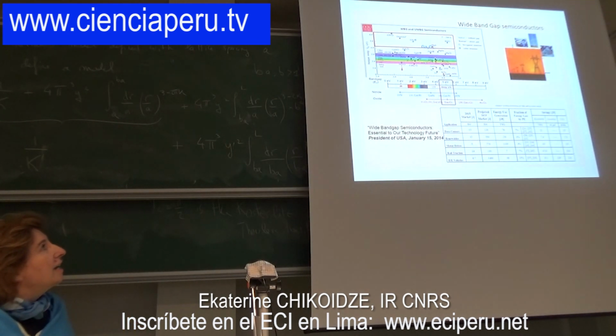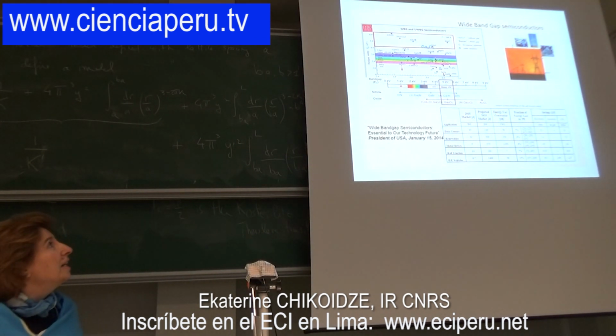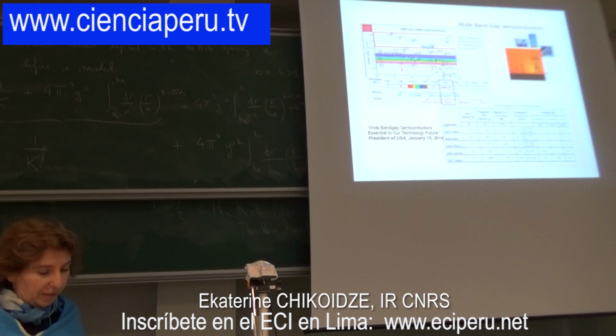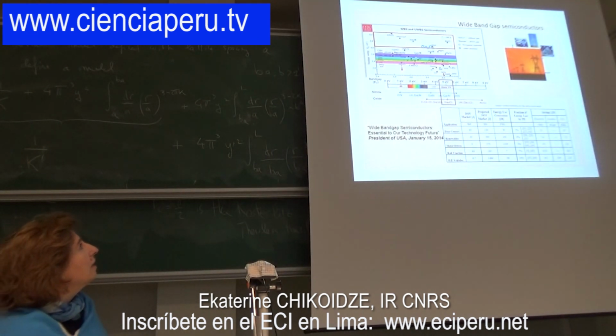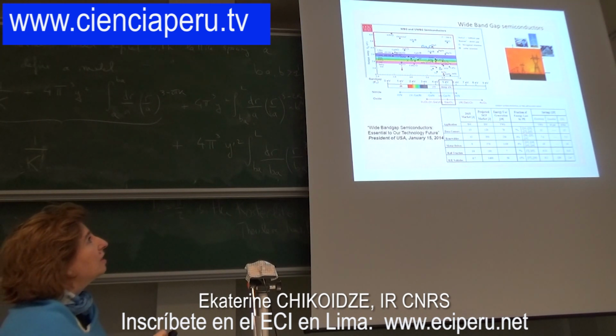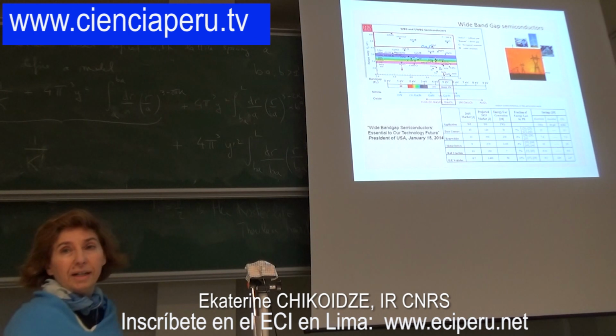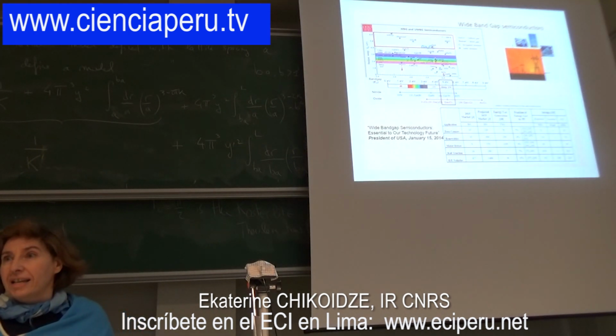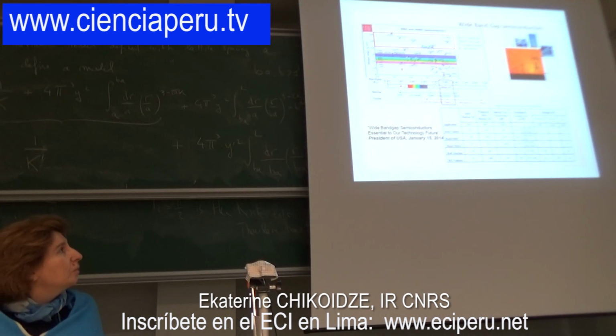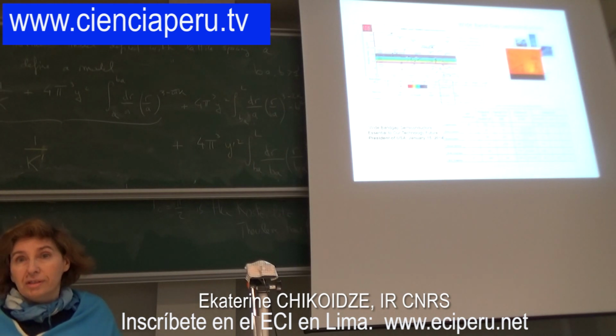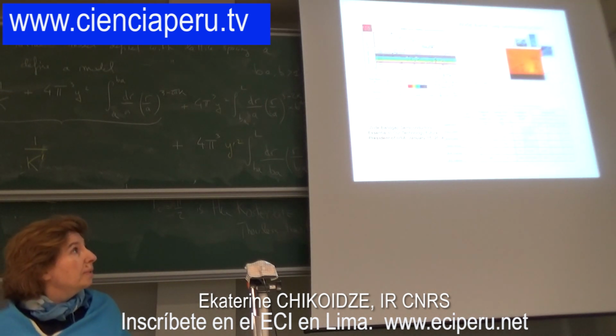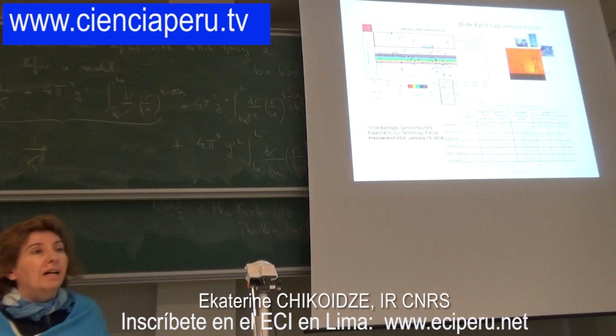And there is also now a very important new family of materials, which we call ultra wide band gap. It means wide band gap materials which have an even higher band gap, more than 4 electron volts. It's diamond, gallium oxide, boron nitride, aluminum nitride, which are very fashionable and under research today. They are important because they can have higher operation temperatures than silicon and conventional semiconductors. The devices based on these materials can have higher radiation hardness, high operation frequency, high voltage operation.